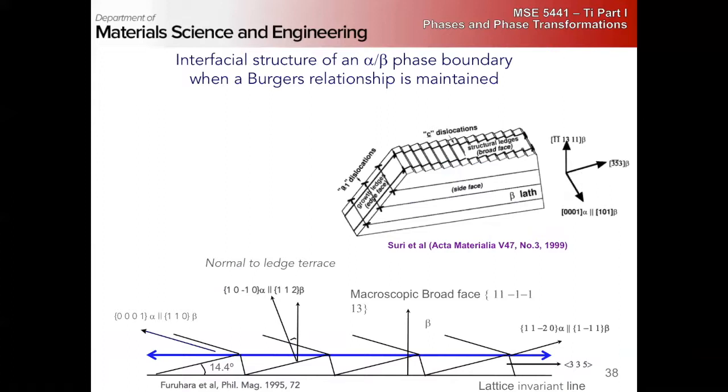So how do they maintain that orientation relationship? Essentially we get the same thing. We get steps that maintain it, followed by little terraces that maintain the orientation relationship, little steps where it deviates, and then growth happens by the motion of these highly mobile, high energy boundaries across to grow the alpha laths, right?